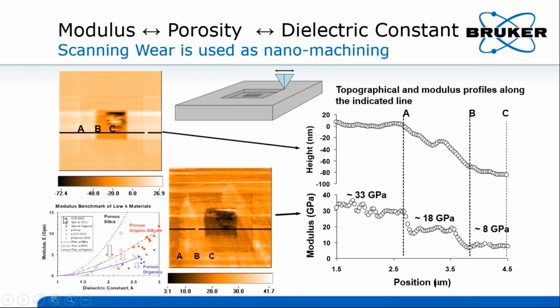Therefore, higher modulus corresponds to higher k, and lower modulus corresponds to lower k. This concept will help us to do the main purpose of this work, which is to figure out the dielectric constant distribution in the thickness direction and check the vertical uniformity due to the UV curing.